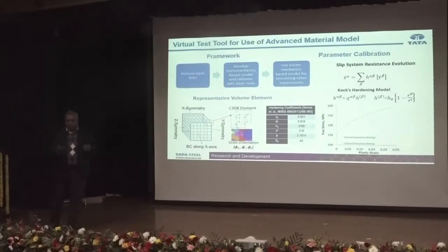Otherwise, if you want random, you can do random also, and then you assume some critical resolved shear stress values initially, and you apply a stress and see whether you are able to simulate a very simple deformation like the tensile test or not. And once you do that, you calibrate some of the coefficients, like the critical resolved shear stress, which is not known a priori. So you start with some assumption and then you calibrate to come to a value which is accurate enough to simulate the tensile test. Now you use the same set of values and start giving different deformation paths to that set of grains.